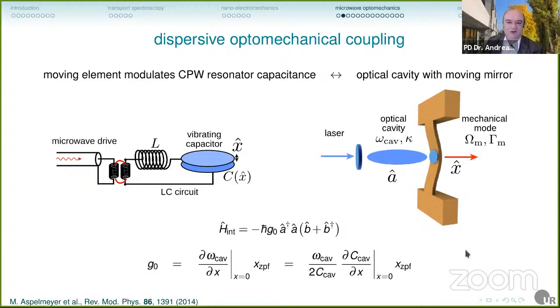But luckily, there's an alternative to that. There's also the so-called field of microwave optomechanics. And it turns out this system here, the laser cavity with the mirror on an oscillating beam, is 100% equivalent to this system here, a microwave cavity, an LC circuit, with a capacitor where one of the plates can vibrate. Both are described by the same interaction Hamiltonian and by the same main coupling constant, this G0, the zero photon optomechanical coupling strength, that describes how much your cavity frequency changes if you shift the mirror by the characteristic length scale of the mechanical harmonic oscillator. And you can also write this down in terms of the capacitance, and then you end up with a similar expression here.